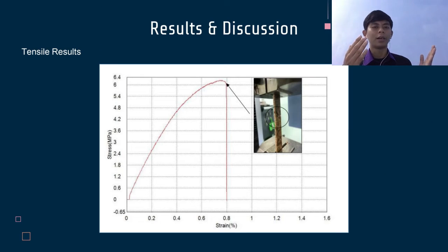So this is my result for the tensile test, where we did almost 24 tests, with each sample repeated 3 times. So there are 24 tests for the tensile result, and then we get the average value. The first graph represents the maximum parameters, where we use the highest value of the weight, which is 10 gram of bagasse. We use the bigger size, which is 10 mm, and the maximum value of PVA, which is 5 gram of PVA, and the highest value of cassava starch, which is 42 gram, and the last one 30% of the glycerol. We mix it up and make a sample and we test it.